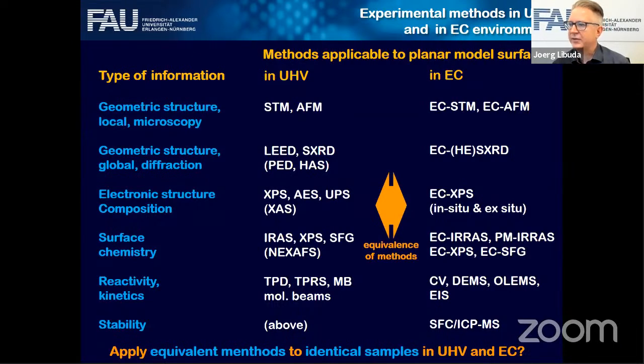If you're looking at other surfaces, the problem may not be as severe. So it depends very much. We're looking, for instance, at oxide surfaces a lot. Oxides can be very tricky. Ulrike Diebold's group has shown that there are very big problems if you're working with oxide and the environment is not perfectly clean. You have traces of carbonic acids in the environment and they adsorb on the surface. You find them. It depends very much on the conditions.